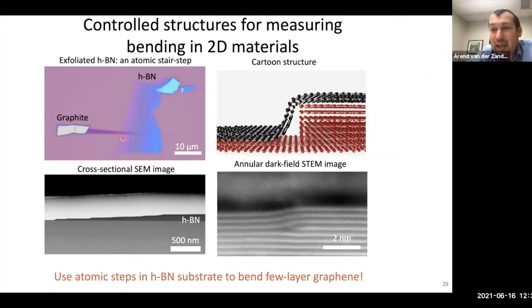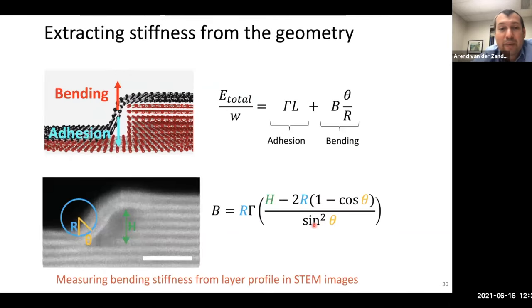Then we take what we call focused ion beam, and we cut into this structure and cut out a cross section. And now here, you can actually see the cross section looking at it from the side. There's our substrate, and there you can see all these little tiny atomic scale steps. If we zoom in on one of those steps, we can now measure and see the lamination. Here we have three layer graphene laminated over a one atomic layer step. And you can see that there's a slight curve to the graphene.